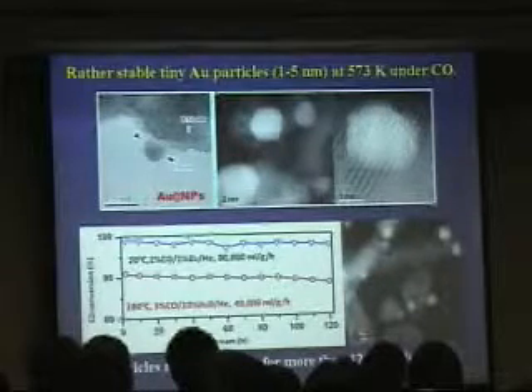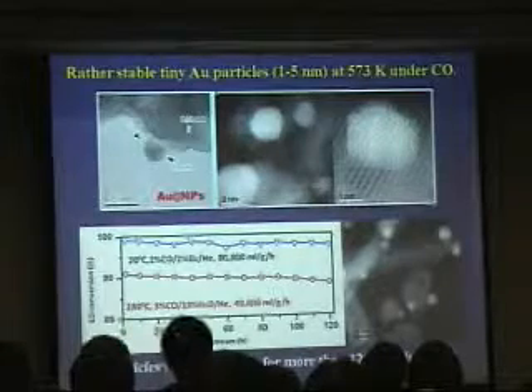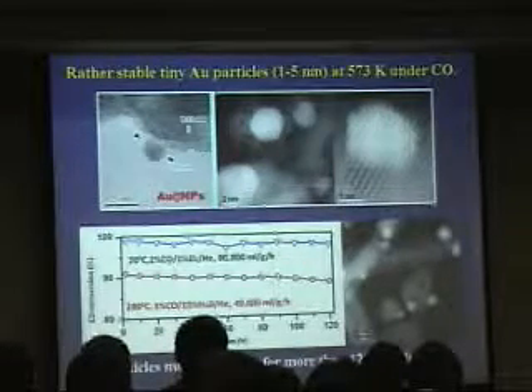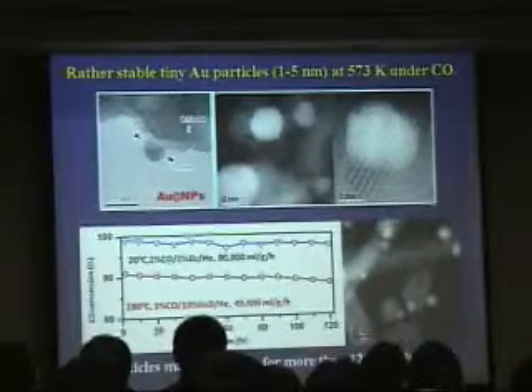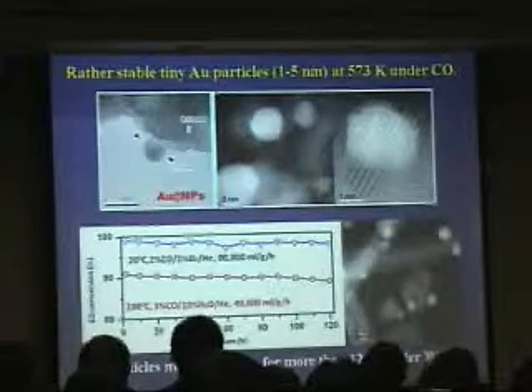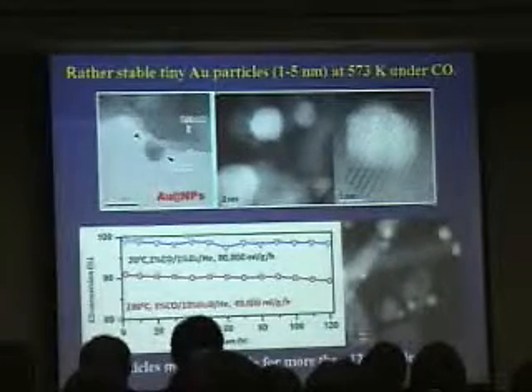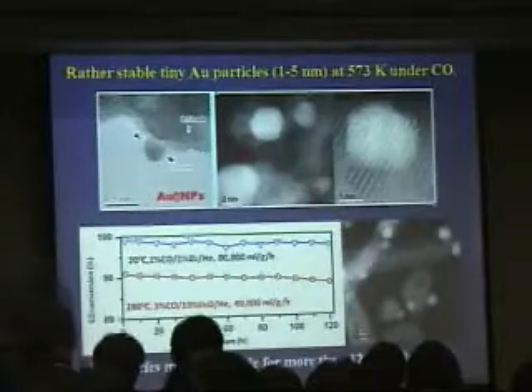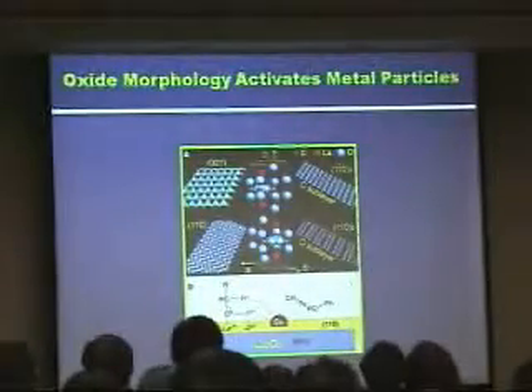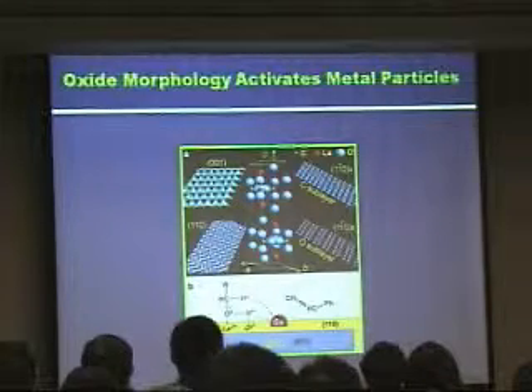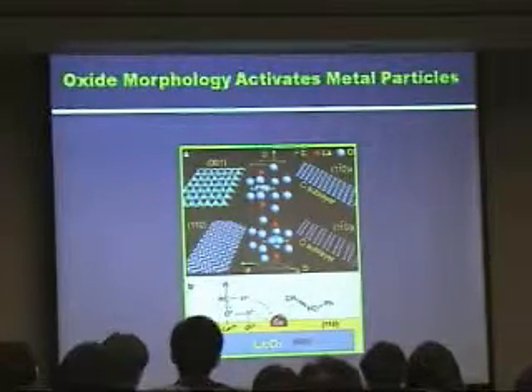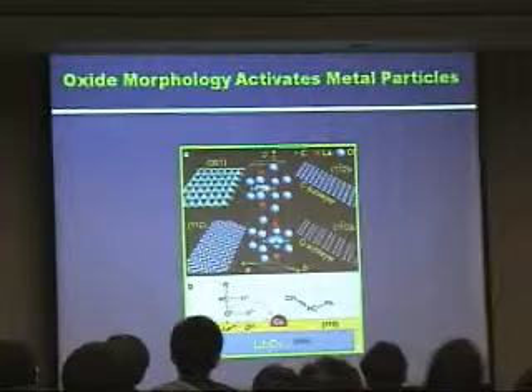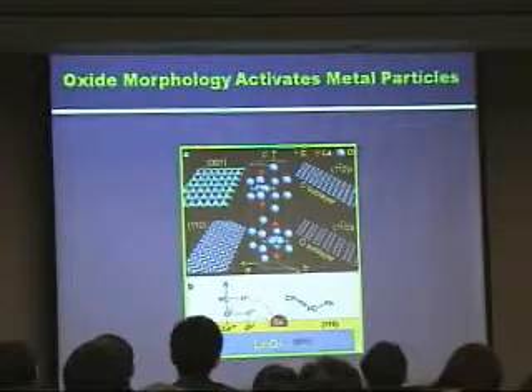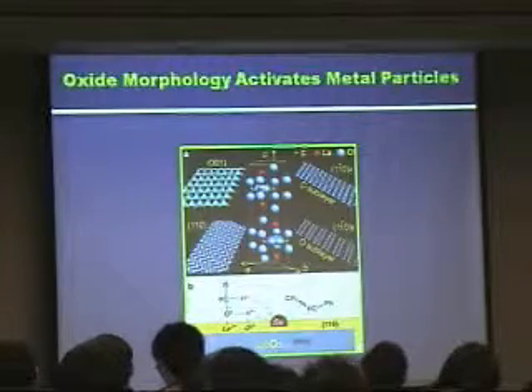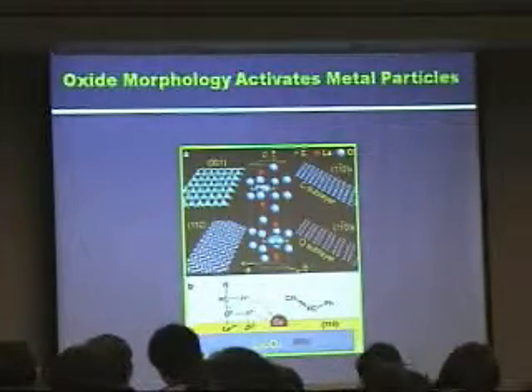So we suppose that changing the shape of the support can partially solve the problem of very small metal nanoparticles by strong chemical bindings. So this is the example of improving the stability of the metal particles by the shape of the support. And finally, I can give you another example, that the shape of the support can also enhance the activity of the metal particles. This is rod-shaped lanthanum oxide to support the copper particles, and we use it for a liquid phase reaction.